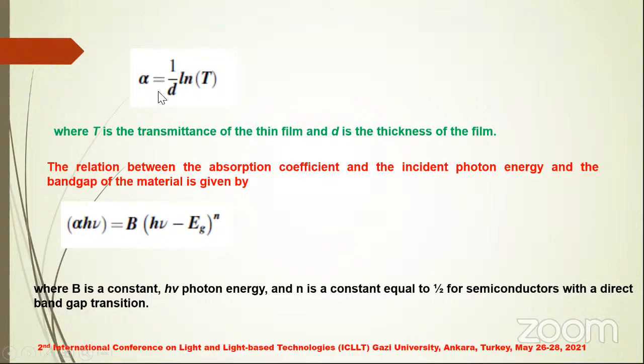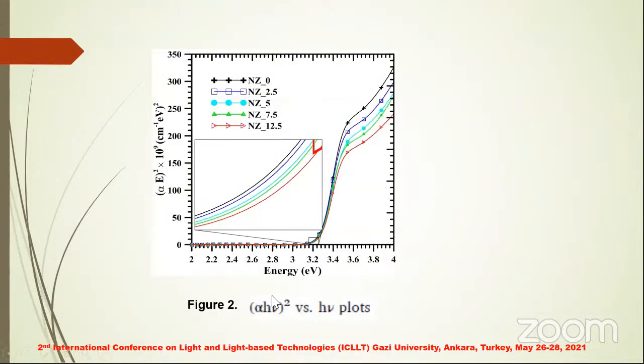The relation between the absorption coefficient, the incident photon energy, and the band gap of the material is given by, where B is a constant, hν is photon energy, and n is a constant equal to 1 divided by 2 for a semiconductor with a direct band gap transition. The energy band gap of the films was found by plotting (αhν) squared versus hν, where the point at which the slope of this graph intersects the hν axis indicates the band gap energy of the film. As seen in figure 2, the energy band gap varies between 3.281 electron volts and 3.274 electron volts.